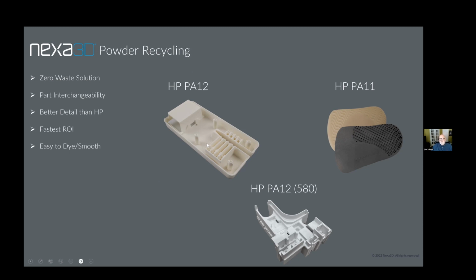And this is not due to anything we're doing. This is due to the HP system, which doesn't have an inert environment and actually oxidizes the powder significantly through multiple runs. So eventually the powder gets a little bit off-white, and the thermal optical sensors on the machine for HP don't like that off-white. So it disqualifies the powder and you start to build up waste. That waste is still in very good health and it works perfectly in an SLS machine. We're able to do that by adjusting parameters, putting that material in our machine, which again, fast cycle, open platform, allows us to produce these high quality parts from waste.